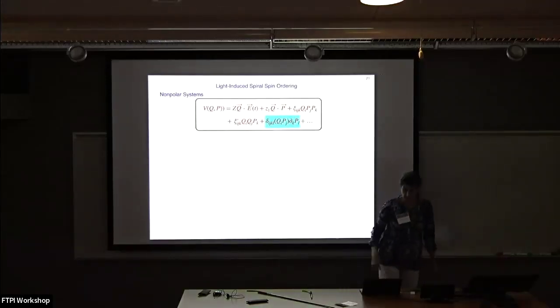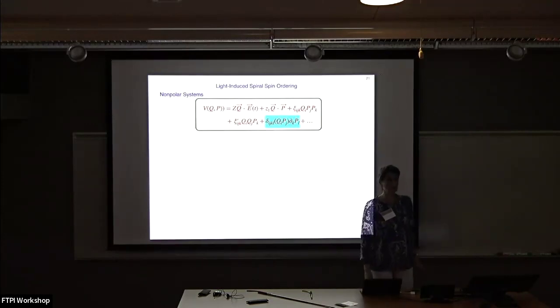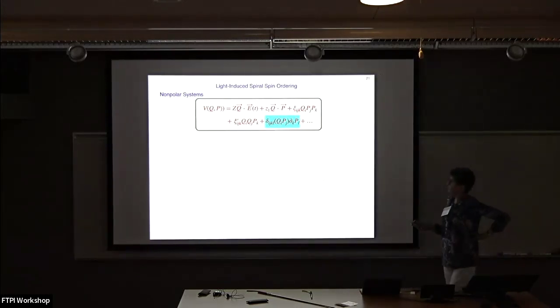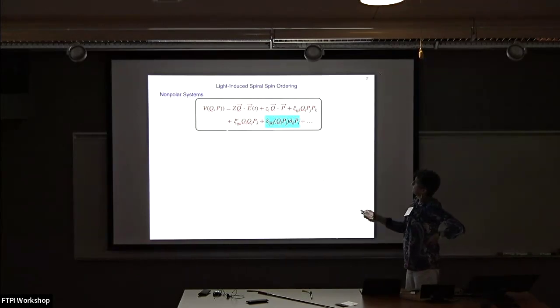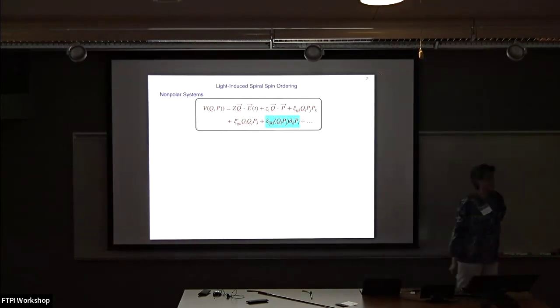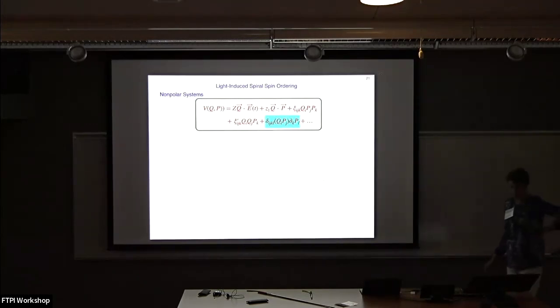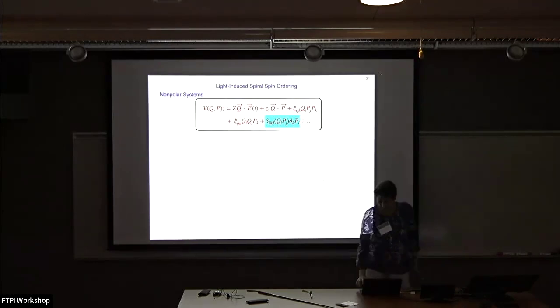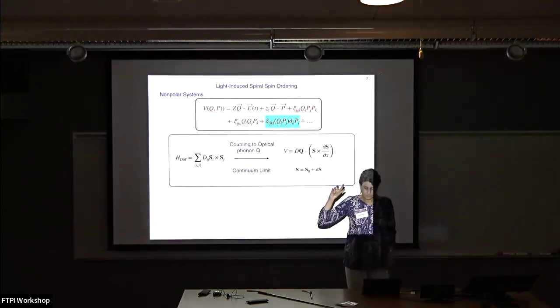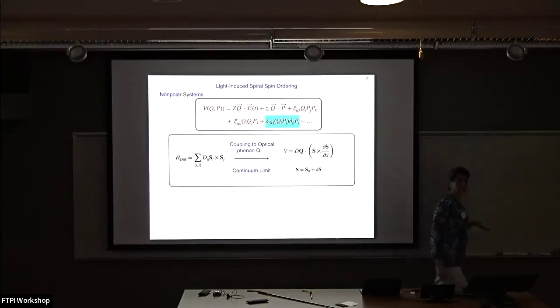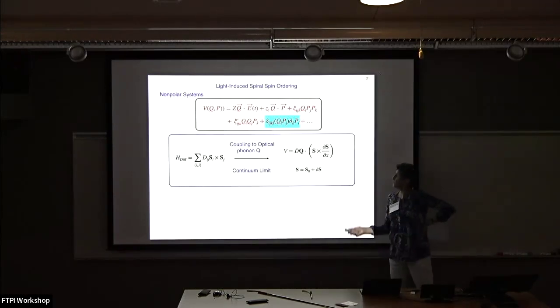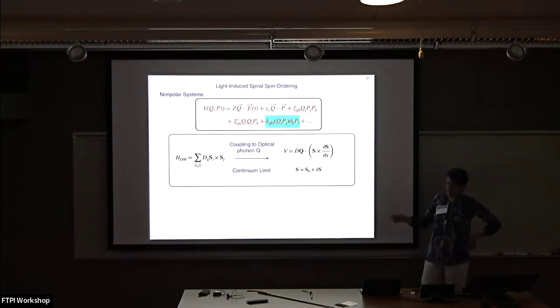Now, just to connect a little bit with Peter's talk, in non-polar systems, can you get this? Well, in non-polar systems, which maintain inversion symmetry, these terms will all be zero, but now this term here comes to the fore. And as I understand it, if you have a frozen Q here, this is called an invariant. But in any case, what we learned is that if you have the Dzyaloshinskii-Moriya interaction and a coupling to a phonon mode Q, we can actually get something like this.